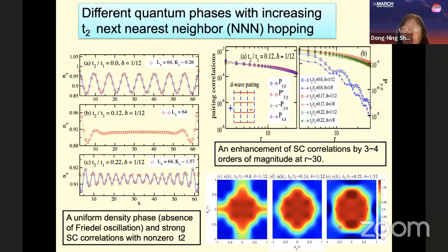For those three phases, the electron Fermi surface has a different shape. We cannot identify where the Fermi energy is, but for larger T2 over T1 the Fermi surface has a near circular pattern. For very small T2 over T1, close to zero, we have an open-like Fermi surface that also breaks rotation symmetry. So these different features characterize the three different quantum phases shown in the phase diagram.